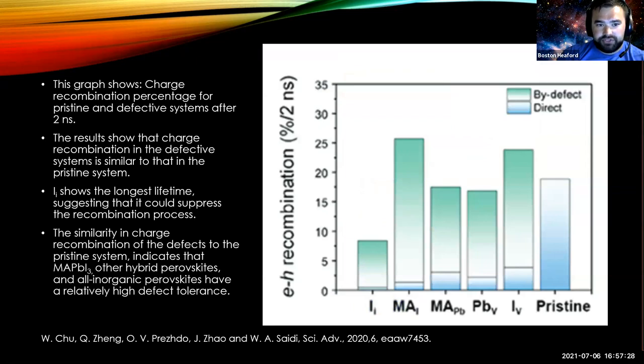So this graph shows the recombination rate of different defects and what percentage of that recombination rate is driven by the defect and what percentage driven by just a direct recombination. And it shows that for many of the defects, the recombination rate isn't that affected, although the iodine interstitial shows the longest lifetime. So charge carriers last longer with the iodine interstitial defect, which is good to know. Maybe it can be implemented in the system somehow.